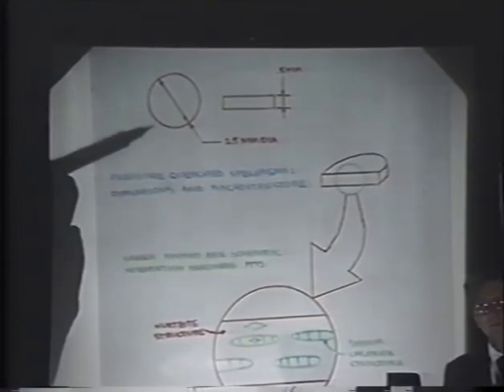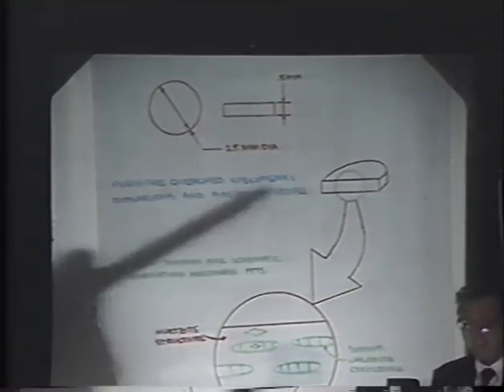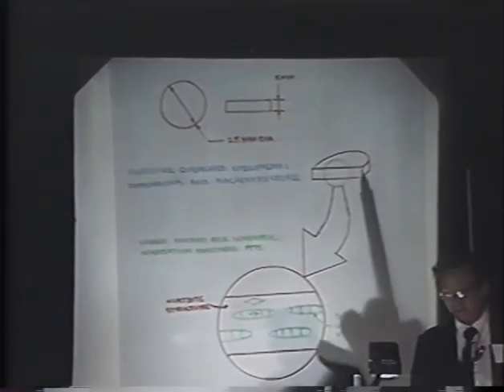Now, pressure quenching works this way. You take the cadmium sulfide and you take it up to in excess of 40 kilobars. And it turns into the sodium chloride phase. When you release the pressure, some of the sodium chloride phase remains, but it remains in a matrix of Wurtzite and zinc blende. And it's the Wurtzite phase here which is unstable.